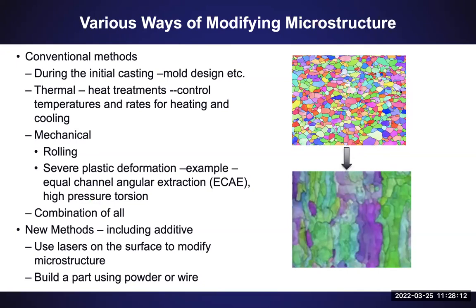So on the top right, I show a micrograph of a conventionally processed material like tantalum. And on the bottom is the same material, but now here we use electron beam additive manufacturing to make this material. And you can see that the grain shape completely changed and the grain size changed. So we're going to use it to our advantage to try to design materials that perhaps do better under dynamic